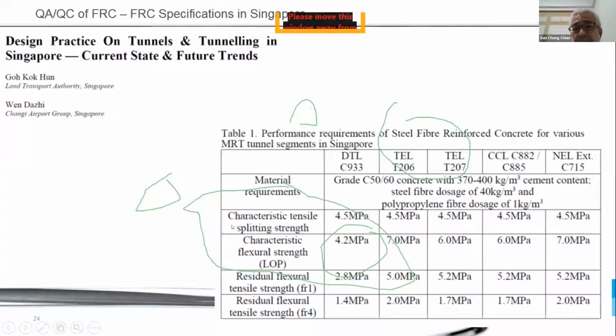It's basically telling you what the specification requirements of fiber concrete in Singapore are. Characteristic tensile strength is around 4.5. Characteristic LOP is between 4.2 to 7. Characteristic FR1 is 2.8, and today it is 5.2. Characteristic FR4 is 1.4 in the first project, and today is 2 MPa. So the requirements for fiber concrete are getting higher and higher.